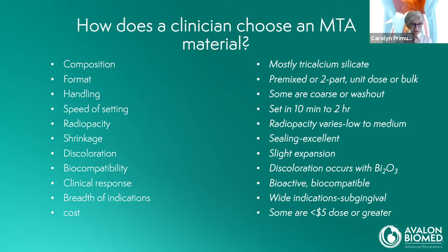The speed of setting goes from about 10 minutes to 2 hours, but you know, they're not as fast as the materials that you may be used to in dentistry, more like impression materials. The radiopacity varies. It goes from low to medium, not as high as some endodontic sealers, but adequate. The sealing for this type of material is excellent because they expand just very slightly.